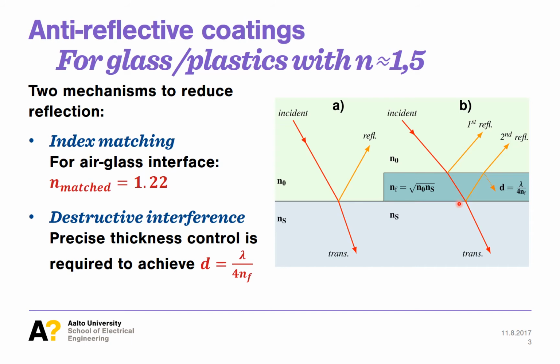The lowest refractive index of an inorganic material is 1.38, that of magnesium fluoride. Some other dielectrics can have an index as low as 1.35, and the theoretical lower limit for the refractive index of a polymer is estimated to be 1.29, which are all still higher than the optimal value of 1.22. It is possible to lower the refractive index of a material artificially by introducing porosity into it, but the pore size should be significantly lower than the light wavelengths in order to avoid scattering.